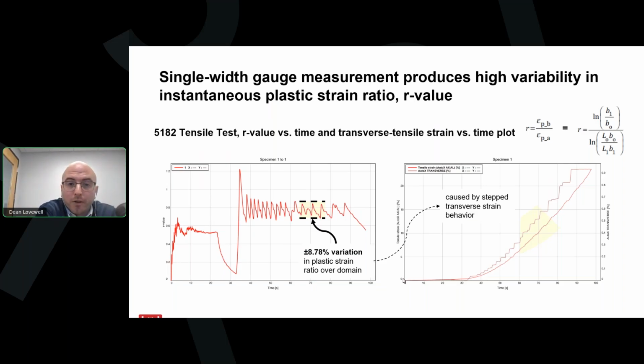So depending on which points are actually chosen for the calculation, you can get large swings in variation test to test. Looking at the plot on the right, we see that the source of that variation is the stepped behavior of the transverse strain measurement. Again, it's capturing the width strain as a band passes the single width transverse extensometer, but it's missing the width strain when it occurs anywhere else. And I've recopied the R value formula here again, just as a reminder of how these measurements affect our calculated R value. B naught is the original width of the specimen, and B sub 1 is the width after the specimen has been strained.